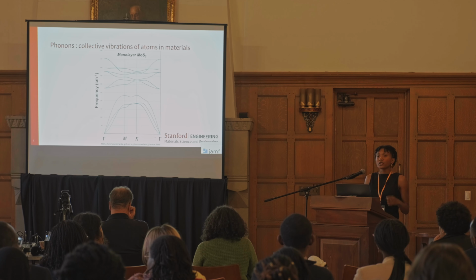And so now we crank up the laser power to use it as a heating source in the system. And to first order, as a function of power, we will again see a redshift, so a lowering of the frequency of the different Raman modes. And this happens for a few different reasons, but one of them is because when we're heating the sample, we have thermal expansion, which is again stretching those bonds, weakening those bonds, and lowering the frequency of the different modes.